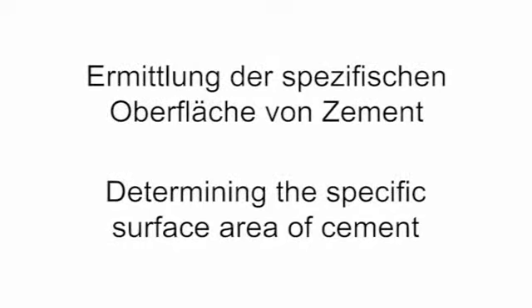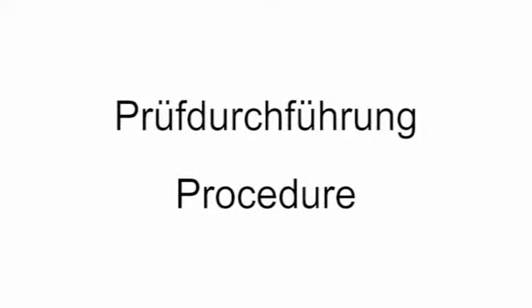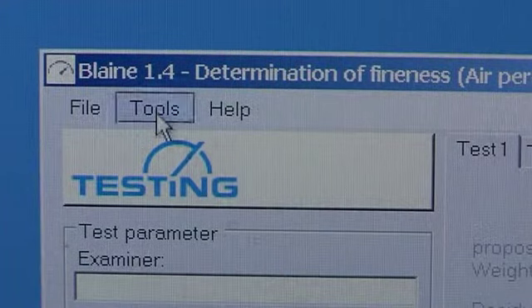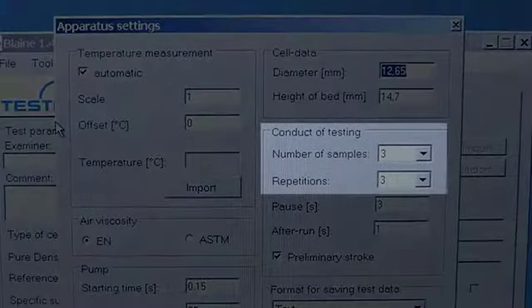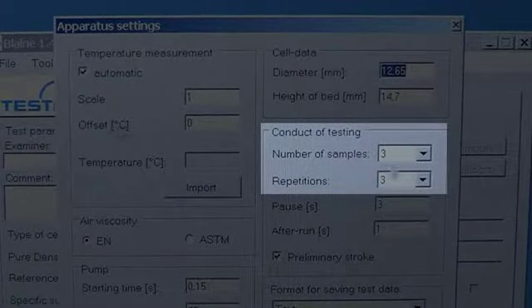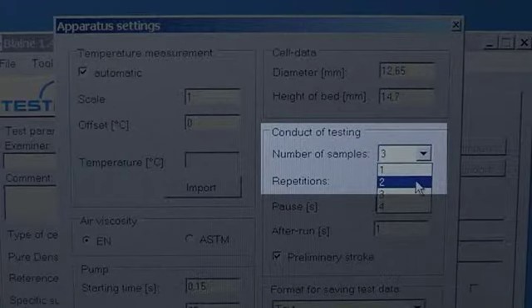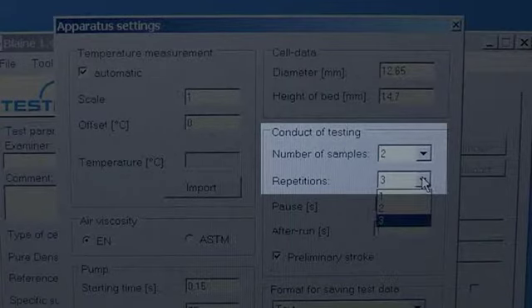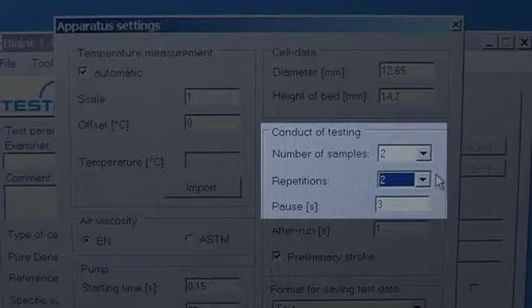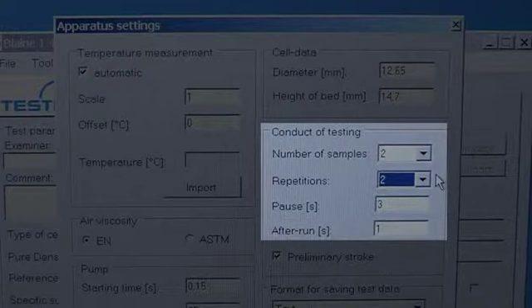Determining the specific surface area of cement. Procedure. Enter the freely selectable test parameters in the menu item Tools, Apparatus Settings. This is the number of cement samples in which the Blaine measurement should be carried out, 2 as a rule. The number of individual tests per powder bed is indicated in the repetition field, 2 as a rule. The break time between individual measurements is indicated in the pause field. The after run field refers to how high the fluid level is drawn in above the upper light barrier.